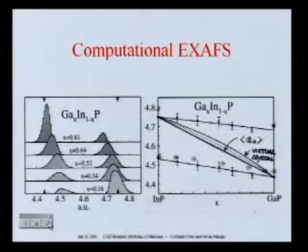And so in this graph, I've put an example of the numbers that we get from the Monte Carlo simulations on the Ising Hamiltonian, and what are actually the EXAFS results that people measure. And you see there is really a very good agreement. Say these are the short gallium phosphide distances as a function of concentration between what the experiment measures and what your thermodynamical DFT is actually predicting.